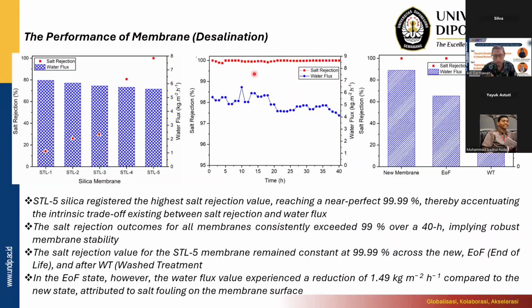the membrane is working very well, and the water flux is quite the same, between 4 and 6 kilograms per meter squared per hour. But if we compare the silica with GO, actually the water flux is very low, because, as I already said before, for the GO the water flux is around 20, but you can see here it is only between 4 and 6 kilograms per meter squared per hour. So one fourth. We can say that the GO membrane is better compared to the silica membrane.